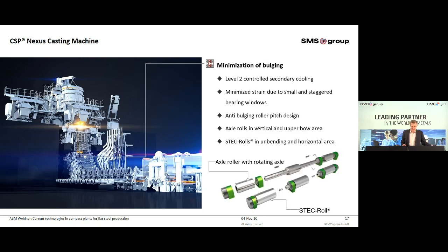At high casting speeds, the strand shell is thin when leaving the mold. To minimize the bulging effect of the strand shell between the rollers, several countermeasures are necessary. The secondary cooling is controlled by a level 2 process model to guarantee a fast strand shell growth without quality issues. The bearing windows between the rollers are small and staggered to minimize strain.